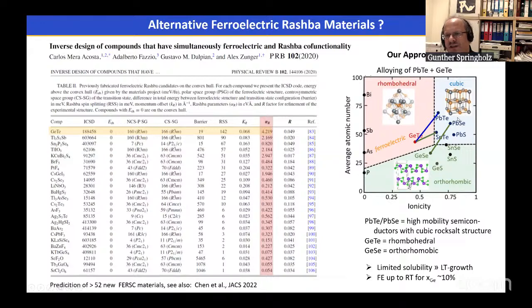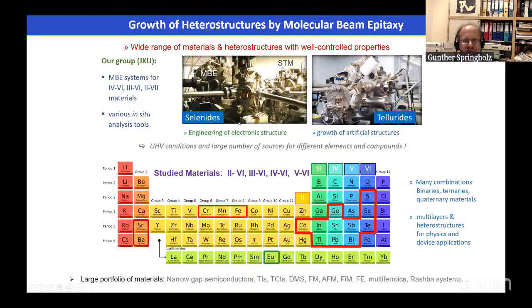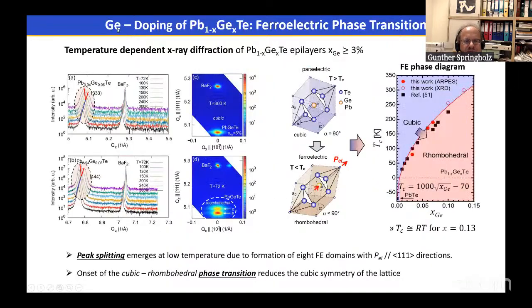A limitation of this approach is that the solubility of germanium telluride in lead telluride is known to be limited to about 10 to 20%. And due to this limited solubility, in order to introduce a feasible amount of germanium into lead telluride, one needs to apply low temperature growth. We do this synthesis using molecular beam epitaxy. We have a lot of different materials we can synthesize with our systems. So we use a germanium telluride source to dope lead telluride epitaxial layers, with concentrations up to almost 15%.